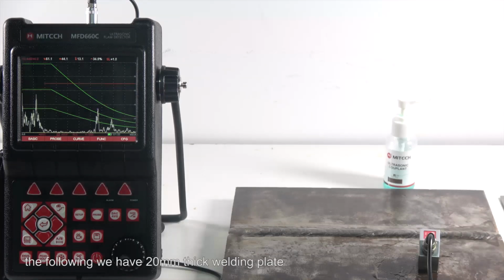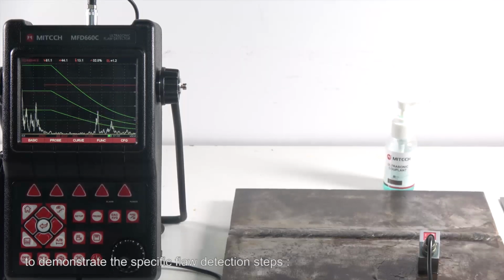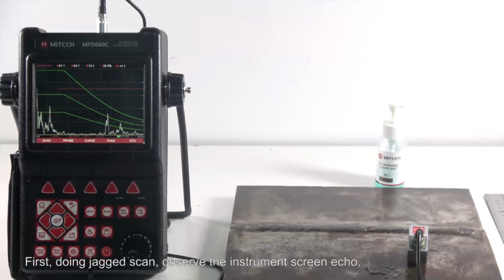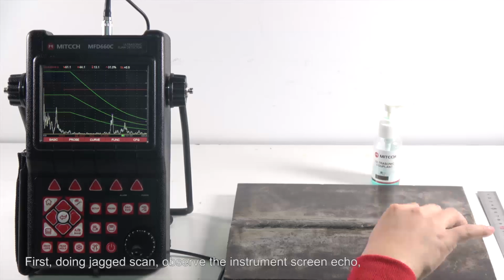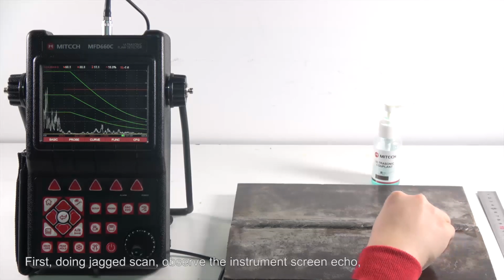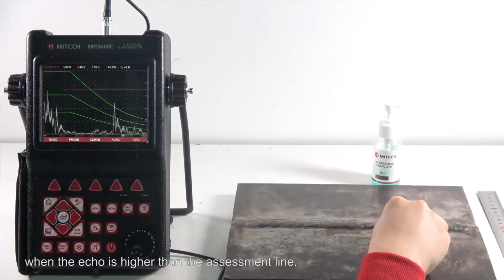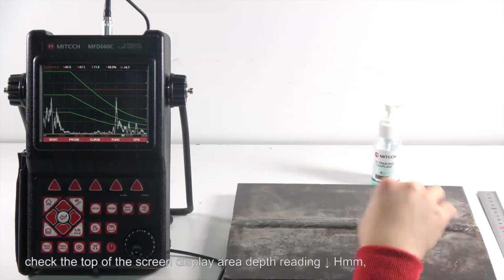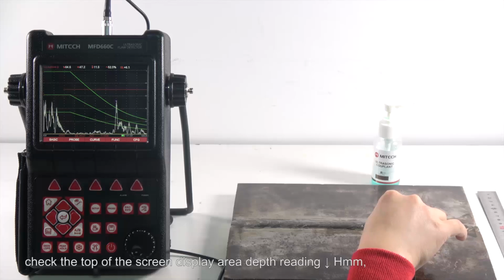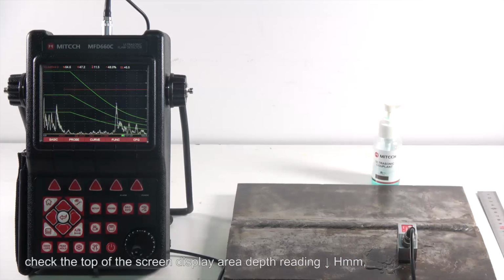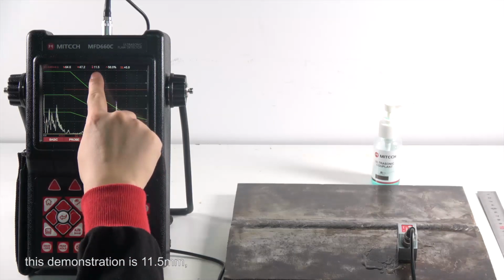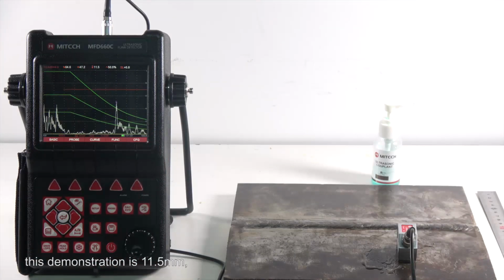The following is a 20 mm welding plate to demonstrate the specific flaw detection steps. First, during zigzag scanning, observe the instrument screen echo. When the echo is higher than the assessment line, check the depth reading displayed at the top of the screen. This demonstration is 11.5 mm.